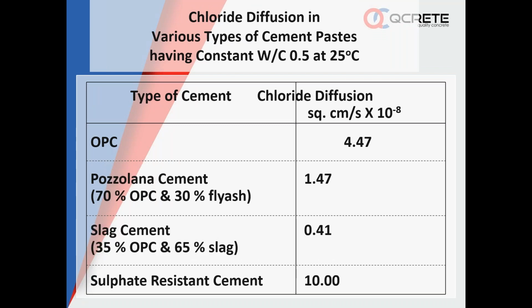Now you can see here chloride diffusions in various types of cement paste having constant water cement ratio of 0.5 at 25 degrees centigrade. You can see the best performance we got was slag cement, that is 35% OPC and 65% slag, which gave the best performance of 0.41. Second best was Pozzolana cement, 70% OPC and 30% fly ash.